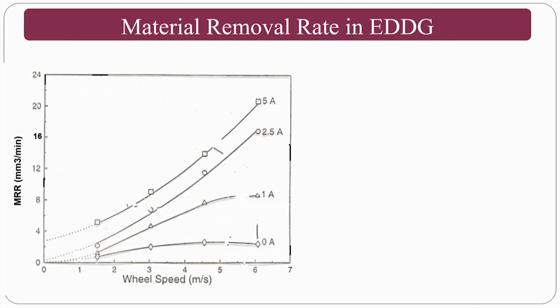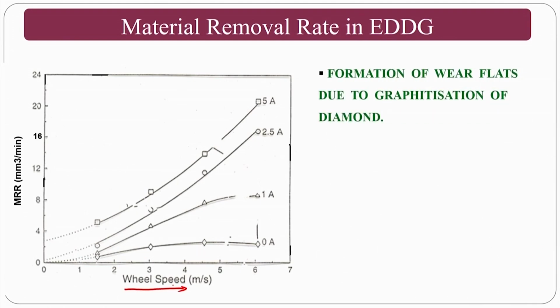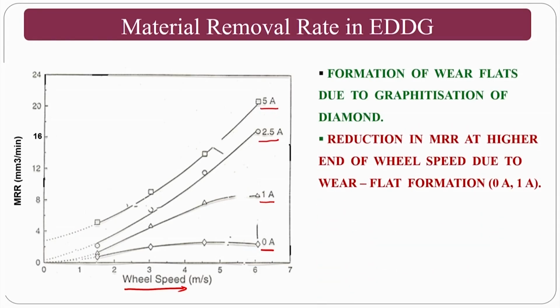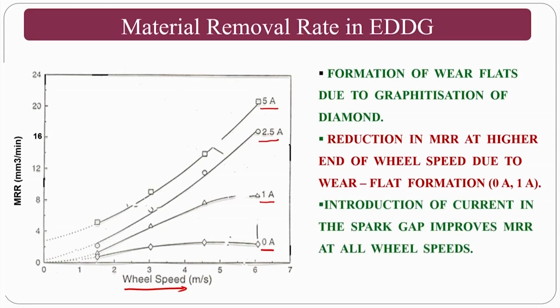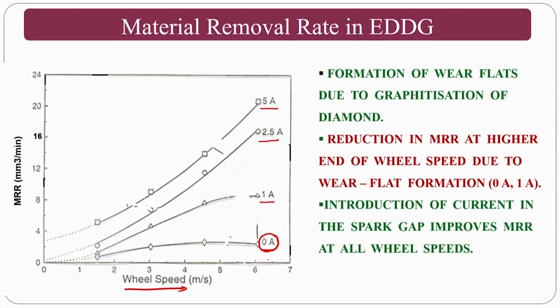So if you see the material removal, as the wheel speed increases, the MRR gradually increases in all current conditions. If you see zero current, that means there is no removal of material using the erosion technique, the spark technique. If you increase the current, the material removal gradually increases. Why is the material removal less at 0 amperes? It is purely a grinding process, because there is no sparking, there is no melting and evaporation. For the same material and grinding wheel combination, you do not have sparking here because your DC power supply is switched off for this particular experiment.